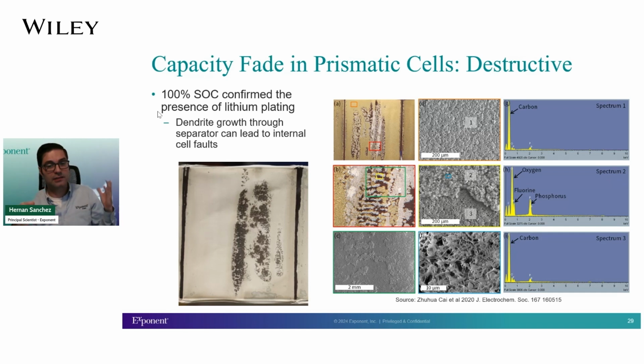And once again, the talk before mentioned how dendrite growth, in this case lithium, like the previous talk was copper, but lithium too, can cause a cell short and can cause degradation, either worse performance through micro shorts, or it can lead to thermal runaway if it's extensive enough.